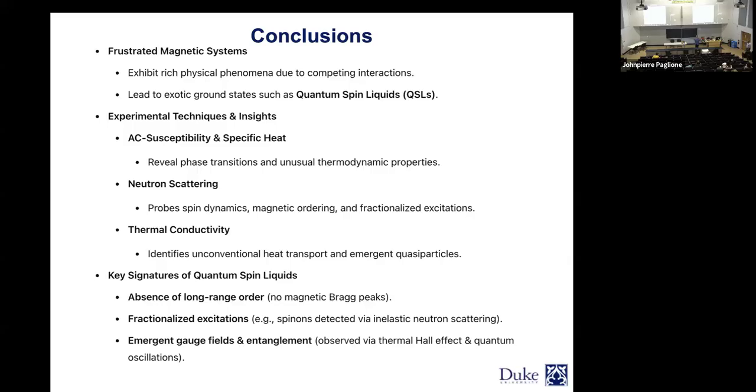So we are talking about the real part of the AC susceptibility as a function of temperature at different frequencies, right? So you would see a peak, and then you change the frequency, and that peak starts to move a little bit, right? If that movement is a lot, it means that you have multiple relaxation times. So you have different domains that have created this glass region. But if you have a very dynamic situation, there's not going to be as much. So with that measurement on your two samples, you would be able to see which one is closer to an actual quantum spin liquid.